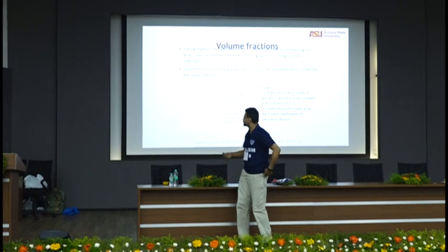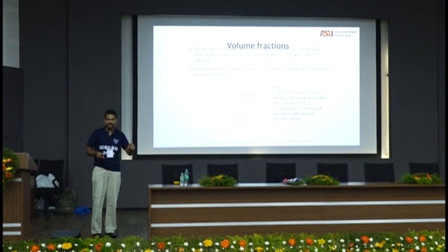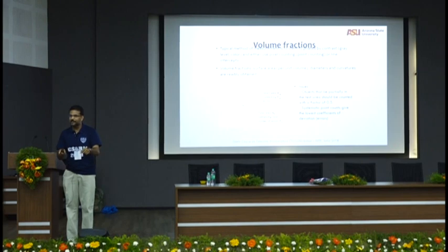So that is called one-point correlation. Basically, you're correlating with just one point because when you throw a dart, it's a point. It's called a one-point correlation function. There is math behind it also. So this is what it is. Objects that lie partially should be counted. So that's why I said if I have something that's lying in between paste and the aggregate, I will give it either paste or aggregate, but the rule of thumb is that if you consider one of them to be the paste, the next one that lies in the paste-void interface should be counted as a void. That's what I'm saying. 0.5 chance. If you count one as paste, the other should be void if it's in the boundary.